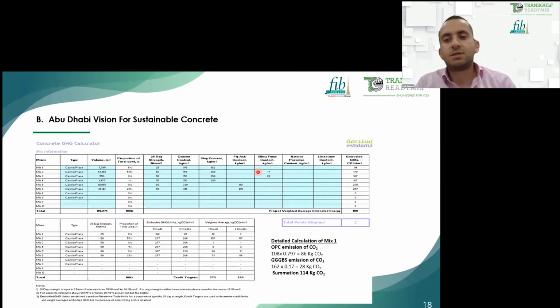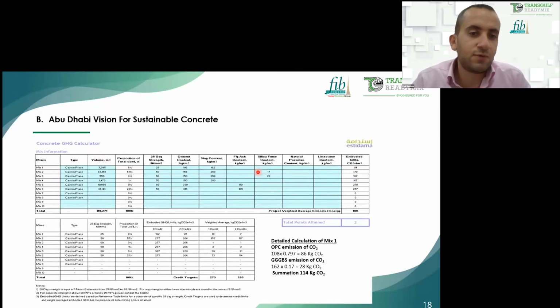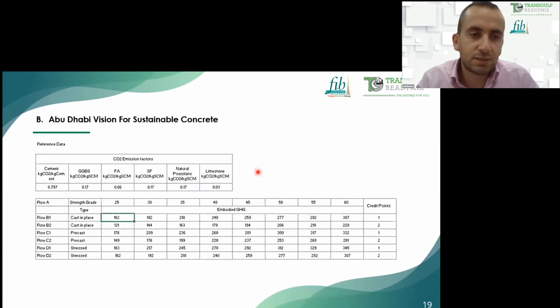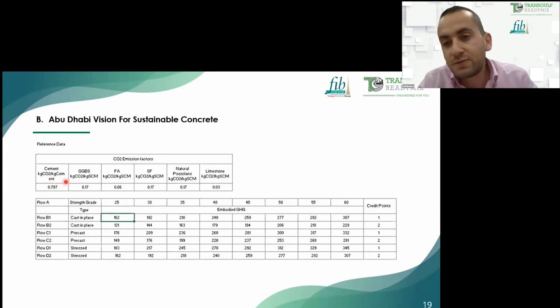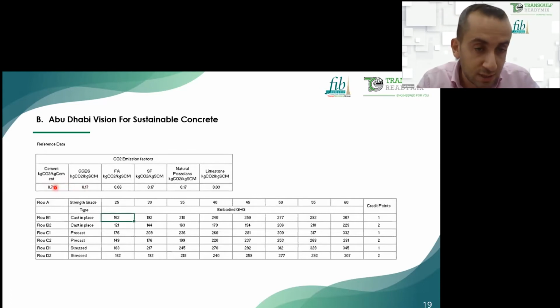Here it shows the calculator. This calculator is for concrete mixes, and I want to go through first the reference data. This table shows how many kilograms of CO2 emission per kilogram of cement. Here we have 0.797, and for GGBS, it's 0.17. As you can see, there's a huge difference in CO2 emission between OPC and GGBS. Fly ash goes down to 0.06 and silica fume to 0.17.